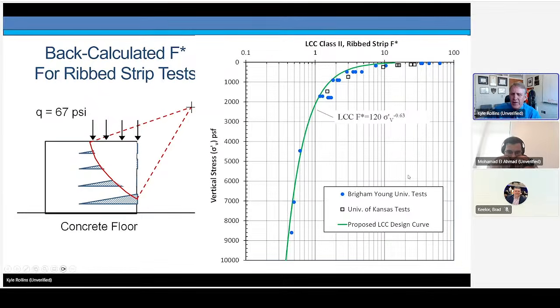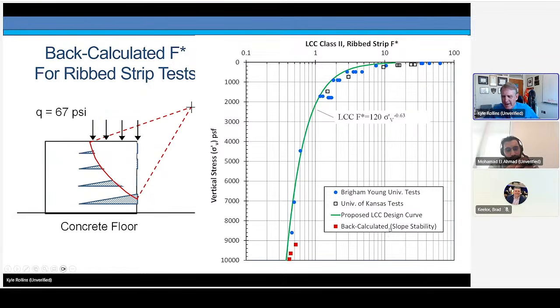So if we do that, I'll show that slide again that showed the pullout resistance in our boundary curve. Here are the back calculated F-star values using the slope stability model. And the back calculated values are in very good agreement with what we got from the pullout tests here. It's 3 tests that we're looking at there.